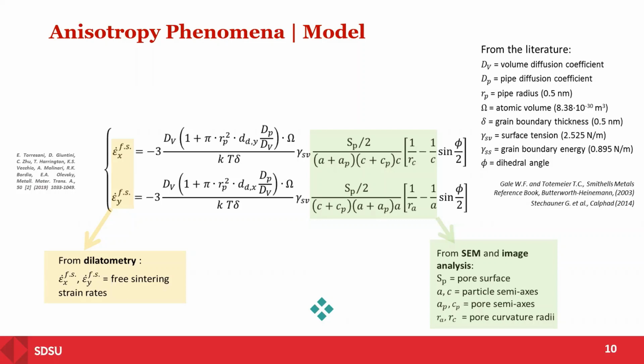So this we get from the dilatometer. All the geometry part we will get from the SEM and image analysis. For the different cases, different temperature treatments, we can, using image software, analyze all these parameters. So the only unknown parameters that remain are the two dislocation densities. So we actually do not use this equation to derive them directly, at least at the beginning, but we use it to derive these two values, which we then try to validate by measuring them experimentally with different approaches, because finding the dislocation density can sometimes be non-trivial. Yeah, and these are the model validation parameters.